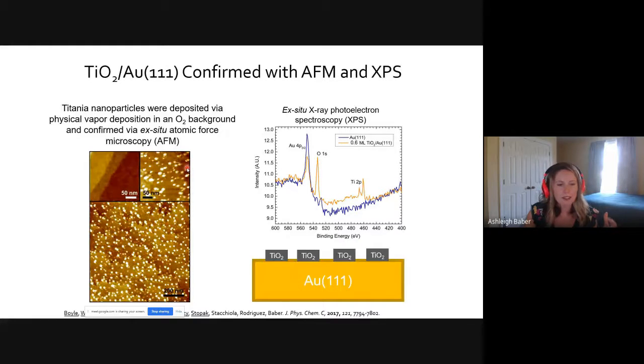I've already talked about this a bit. We deposit titanium onto the surface in an oxygen background and anneal that at high temperatures to get these particles across the surface. And then we took the sample. We don't have XPS on our chamber, but we took this to Virginia Tech and were able to confirm the presence of titanium and oxygen. And then we have these nanoparticles across the surface. We're able to do ex situ AFM at JMU.